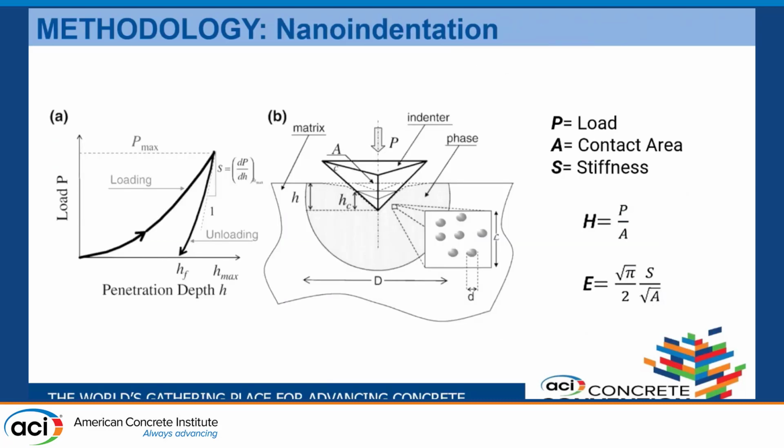My other methodology is nanoindentation. Nanoindentation pierces into a specific material and determines its micromechanical properties, considering the unloading curve of the displacement. When the indenter penetrates the material, it displaces some mass, and from that displacement I'll be able to get two properties: the hardness and the elastic modulus. These properties are the result of the specific load applied, the contact area, and the stiffness of the sample.